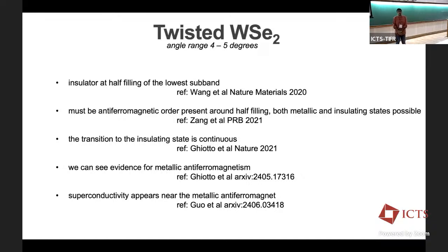One final question from Oscar, and then we should move on. How sensitive is your insulator at nu equal to -1 to the external magnetic field, particularly if it's perpendicular? Yeah, that's an interesting question. It's fairly sensitive. By about 3 or 4 Tesla, you generally lose this insulating phase.